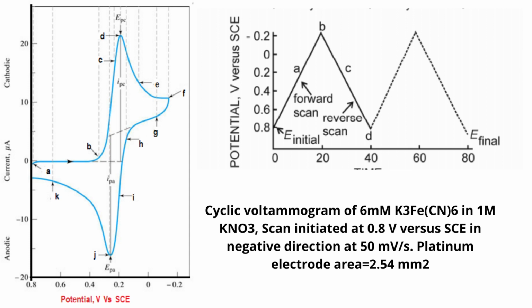A platinum working electrode is in a solution containing 6.0 millimolar potassium ferricyanide as the electroactive species in 1.0 molar potassium nitrate in water as the supporting electrolyte. The potential excitation signal used to obtain this voltammogram is shown in the figure, but with the negative switching potential of minus 0.15 volt. The initial potential of plus 0.80 volt applied at A is chosen to avoid any electrolysis. The potential is then scanned negatively, forward scan, until it is sufficiently negative to reduce ferricyanide.